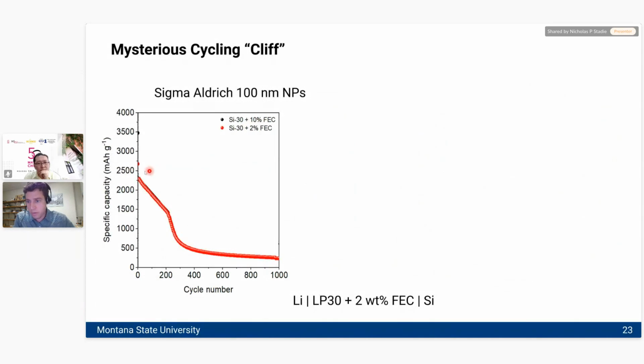And we had never seen this before with graphite, for example. And so we spent a lot of time wondering about it. Basically, what would happen is that you'd get a kind of linear trend in capacity fade, but then all of a sudden it would fall off a cliff, and then it would level out eventually, but you'd get a very dramatic loss of capacity at a certain cycle number, just around 200.